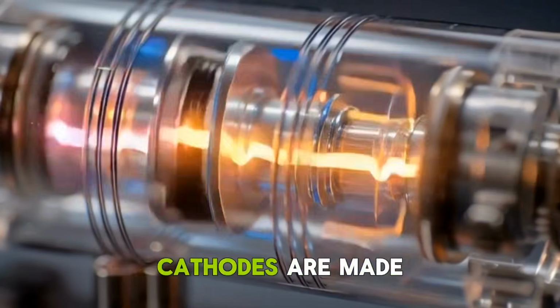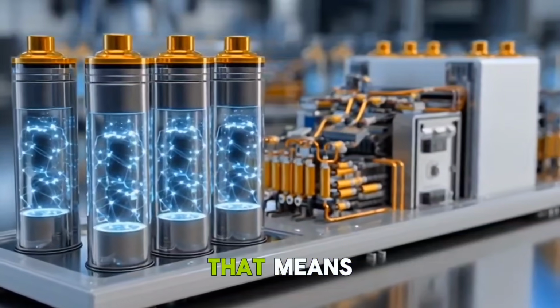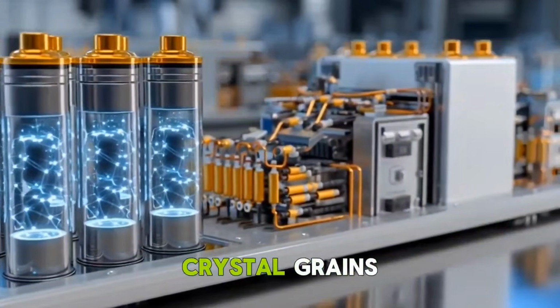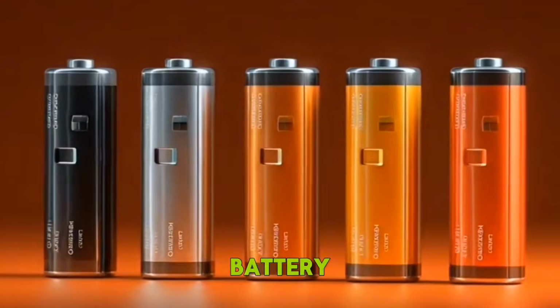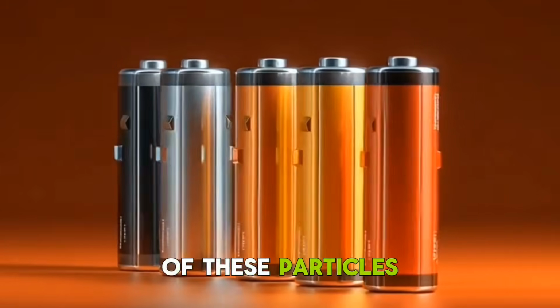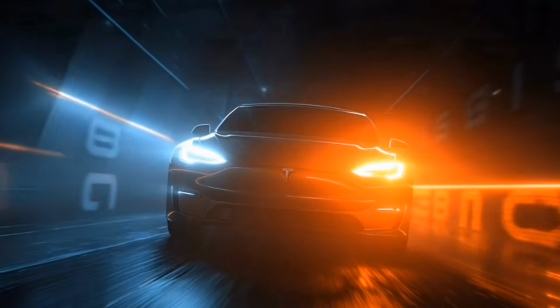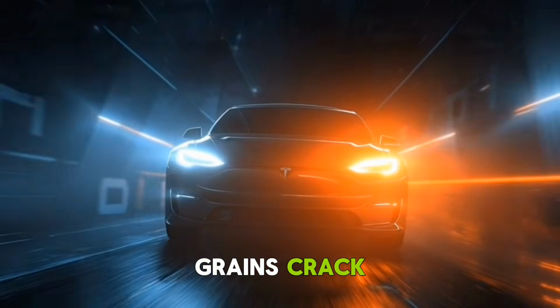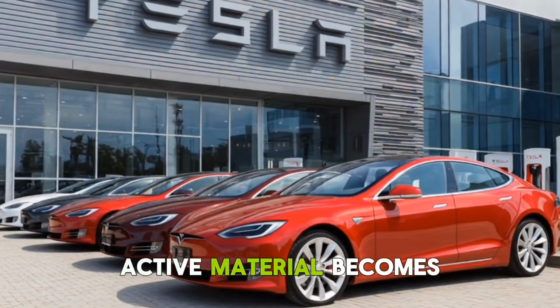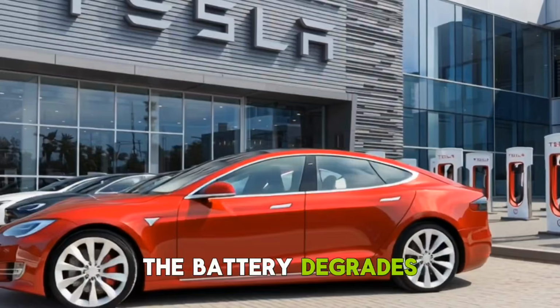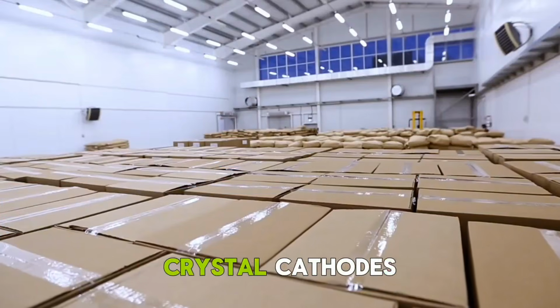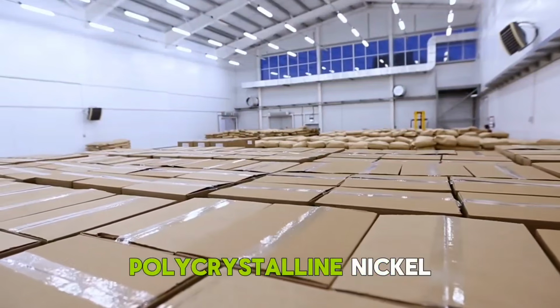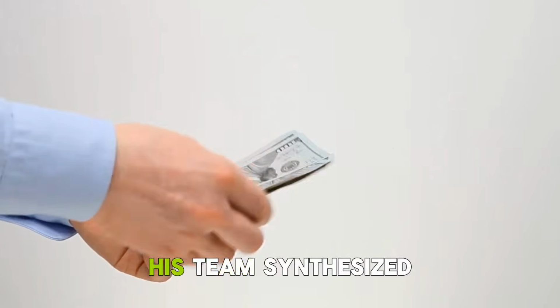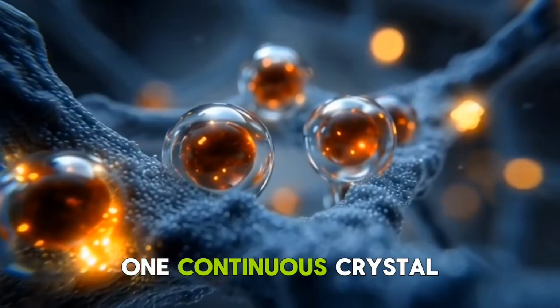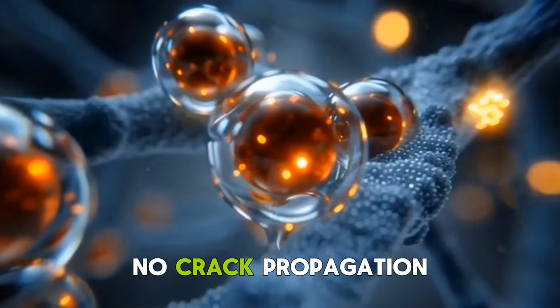Traditional lithium-ion cathodes are made of polycrystalline particles. That means each particle is made up of thousands of tiny crystal grains. When you charge and discharge the battery, lithium ions move in and out of these particles, causing them to expand and contract. Over time, the boundaries between the grains crack, the particle fractures, active material becomes electrically isolated, and the battery degrades. Dahn's solution: single crystal cathodes. Instead of using polycrystalline nickel, manganese, cobalt particles, his team synthesized single crystal NMC532. Each particle is one continuous crystal lattice, no grain boundaries, no crack propagation.